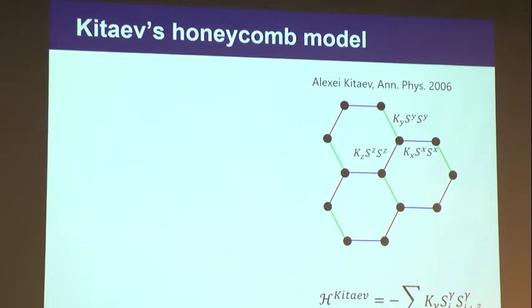So the idea of the Kitaev honeycomb model is this. Take a honeycomb lattice. A honeycomb lattice is not a geometrically frustrated lattice. It's a bipartite lattice. You can actually have Néel ordering on a honeycomb lattice. But what's unique is that Kitaev proposed a Hamiltonian that takes advantage of the honeycomb lattice, where you have three bonds, and each of these three bonds has its own unique magnetic interaction. That's the unique thing about Kitaev's honeycomb model. I'll come back to this a little bit more later.